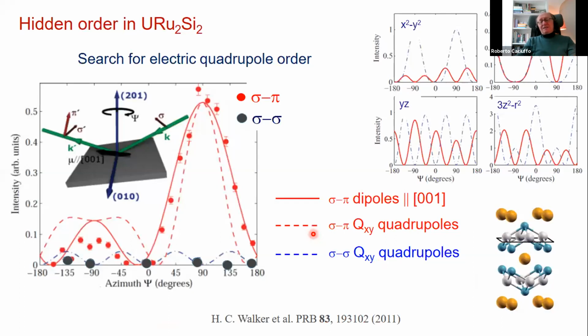Well, the results of X-ray diffraction show the presence of superlattice reflections. For instance, here the azimuthal dependence of the 201 peak. But the azimuthal dependence of the intensity of this superlattice reflection and the polarization analysis are explained only by assuming a magnetic moment along the z-axis, as already shown by neutron diffraction. All models based on ordering of electric quadrupoles of the different allowed symmetries and different motifs provide a profile which is not compatible with experiments.